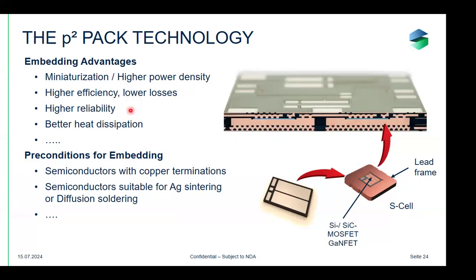So we could also show that we have an extremely high reliability. So typically, if a power electronic module fails in a power cycling test after 100,000 cycles, we could already show millions of cycles with the same parameters. Even if you go to a higher delta T, to higher thermal differences in the switching, you can show extreme high reliability of this technology. And kind of a surprise, everybody's asking, how do you get the power out of the PCB if you have the power inside the PCB? We can do it better than a typical power module because the thermal resistance is designed to a value which is actually lower than some of the best power modules in the market.